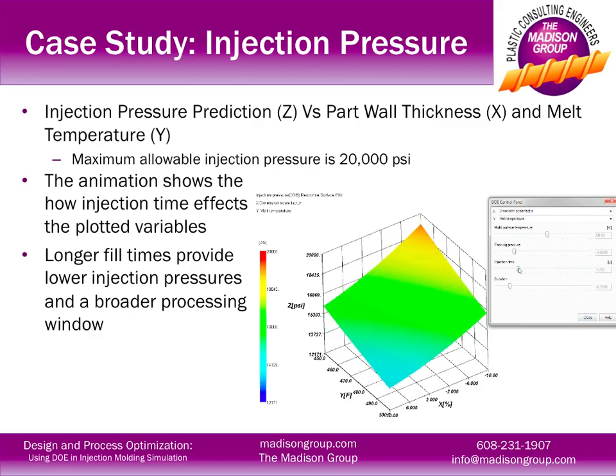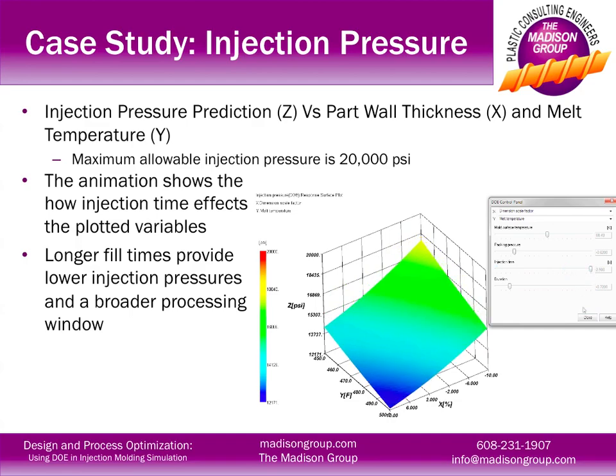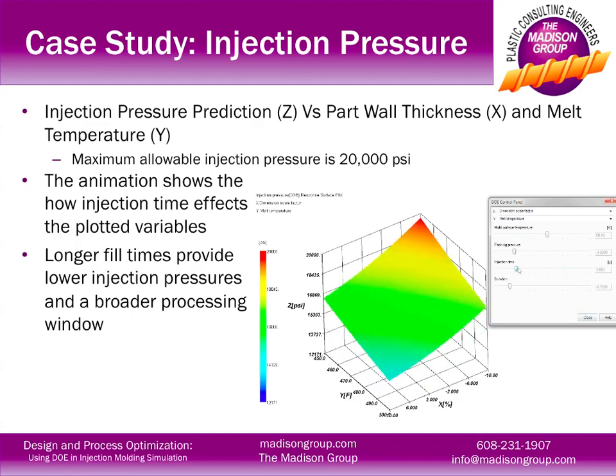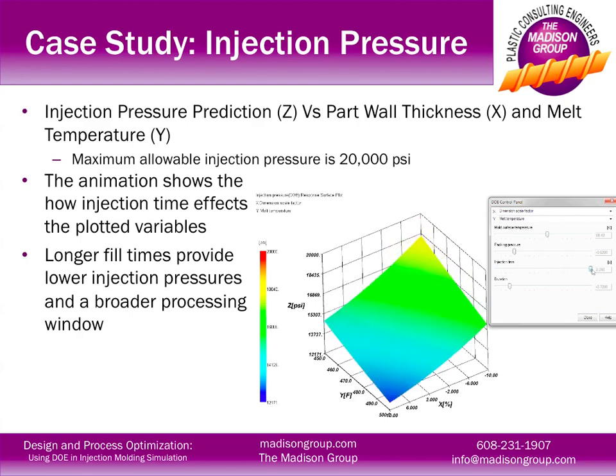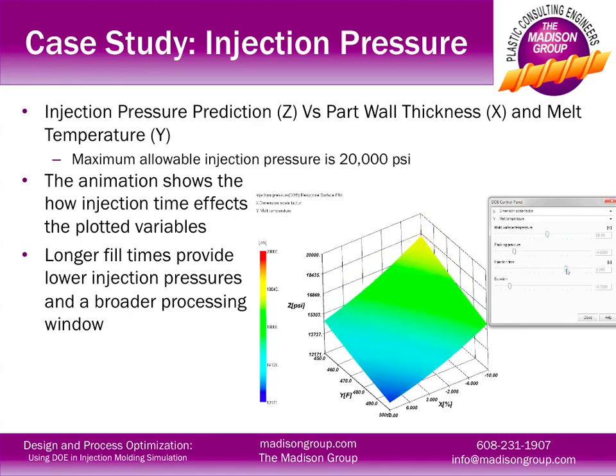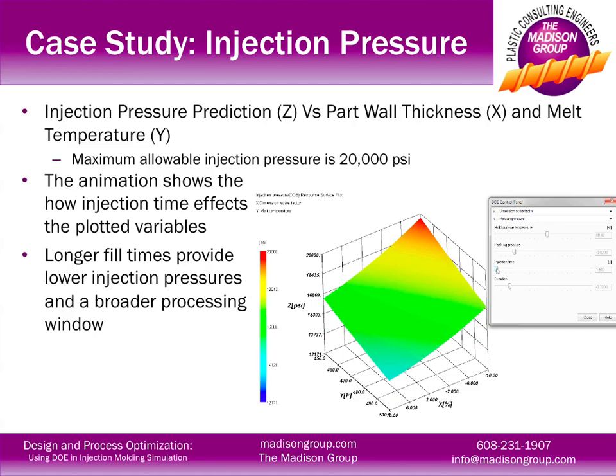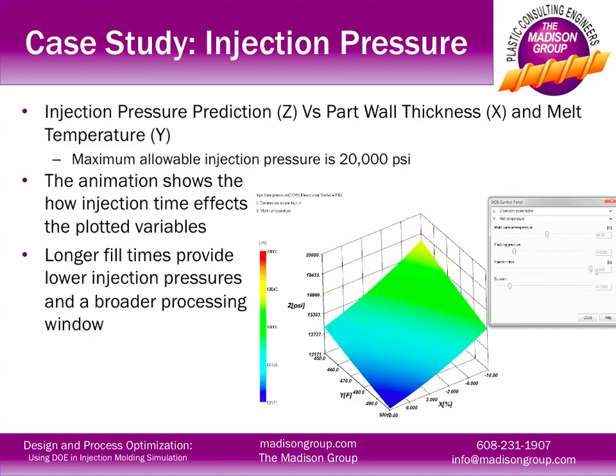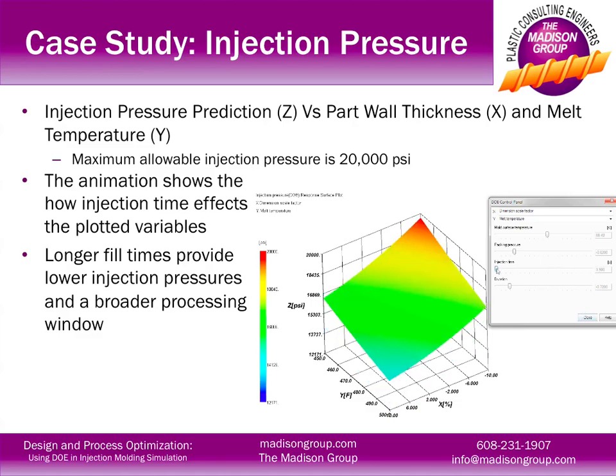We can see very quickly that the container can be molded under the 20,000 psi limit. The plot also shows that if we increase our injection time, the injection pressure is significantly reduced and the processing window can be expanded. The surface response plots created with a DOE analysis allow for very quick and effective interpretation of a part's processability, and their interactive nature allows for quick optimization of the processing window.